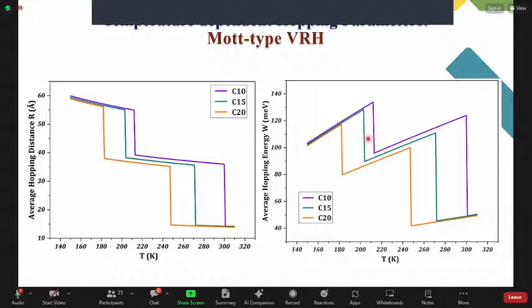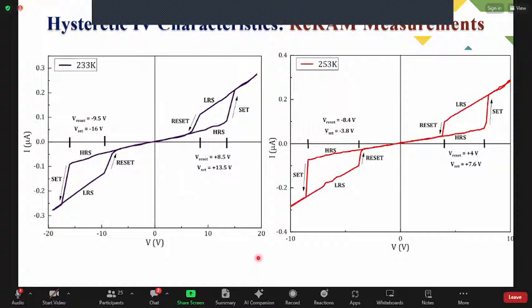This also shows that from that we have calculated hopping distance, average hopping distance, and average hopping energy in the variation of temperature. Now the main characteristic, which is RRAM based measurement, we have done the hysteretic IV characterization for temperature dependency. So we can see that starting from 233 Kelvin, which is lower temperature, we are going from lower temperature to high temperature. We can see that it is showing a window. So it is showing a very good window, and also it is showing the set and reset mechanism.